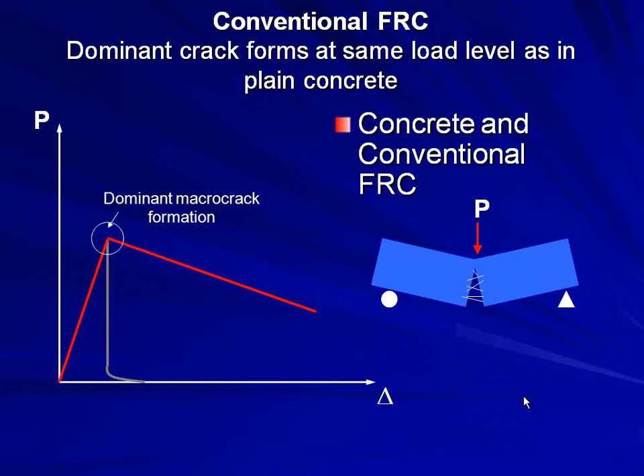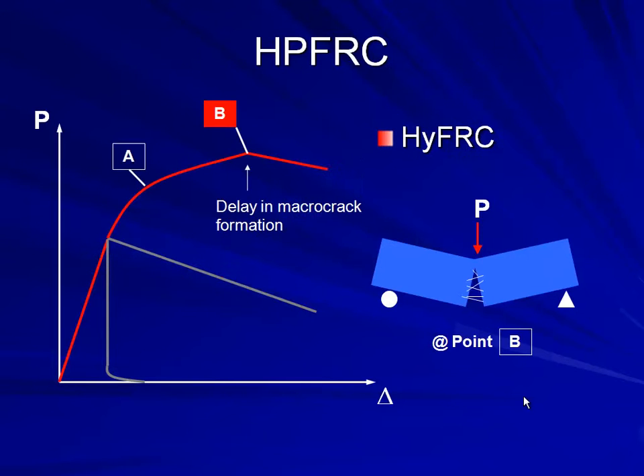Now, in comparison, a high-performance fiber-reinforced composite, and I have the example here. In this case, your dominant crack does not occur here anymore. It is all delayed all the way up to a higher strain level. Now you can decide for your composite how far you want that dominant crack, at what strain level you want it to occur. In our case, the hybrid fiber-reinforced composite, we designed that the dominant crack will occur beyond the yield strain of the steel. Your steel yields at 0.2%. Our hybrid fiber-reinforced composite forms the dominant crack at 0.6 to 1% of strain. So you're really delaying that dominant crack to much higher load levels.